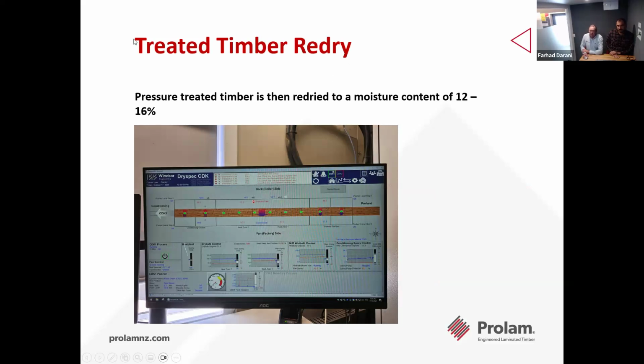And then we have to re-dry the timber after it's treated. So we're re-drying it back again to a moisture content of 12 to 16. And this is a little overview of our continuous drying kiln. So this is your preheat end coming through here. And this is the proper kiln section in the middle here, and then a conditioning section on the way out here.